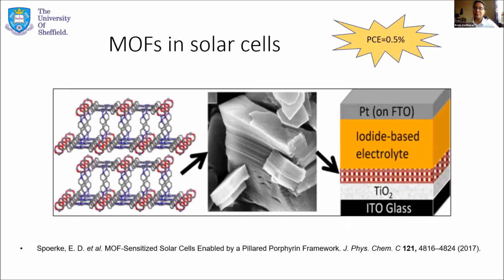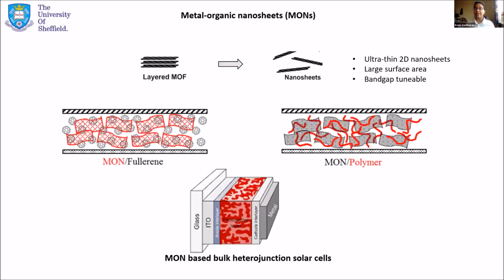They had a brief time of being tested in dye-sensitized solar cells, where they were used to have a systematic arrangement of the dye molecule in order to reduce recombination losses. But their 3D structure makes them limited for applications in thin film solar cell technologies. So in our group, what we focus on is taking a layered MOF structure and exfoliating it into nanosheets. What we do here is expose the surface area of these materials by having them in nanoscopic dimension, and this also enables them to be easily blended with fullerenes and polymers, and thereby provide easy integration into thin film solar cells.